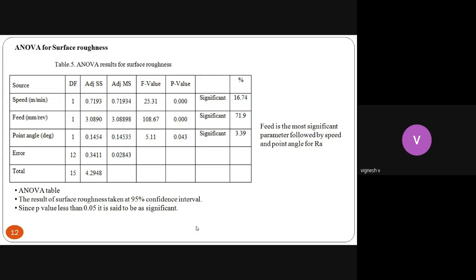And by seeing that percentage, we can analyze which one is the most significant parameter out of the three parameters chosen. So the ANOVA results suggest that the feed is the most influential parameter for the surface roughness, followed by speed and then the point angle. So the point angle is the least influential parameter for the surface roughness. And the ANOVA analysis was done at a 95% confidence interval, that is, out of 100, 95% of the time we obtain the true mean values throughout the operations.